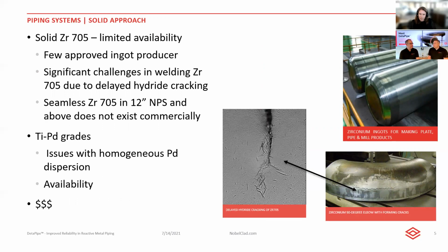Right. Some of the materials out there for construction, because you need the high reliability and the high corrosion resistance of the different materials, you land on things like alloyed versions of titanium and alloyed versions of zirconium to increase the strength and reduce the wall thickness of the metal. Yeah. The metallurgical processing of those materials can be problematic. Small inclusions, impurities of the ingots, when they get rolled out in a raw form, only get worse when you go to fabricate them, and then can even be catastrophic if they get into service. And so things like welding solid zirconium 705, for example, can be tough because you run the risk of having what you see on the screen there, delayed hydride cracking occurring.